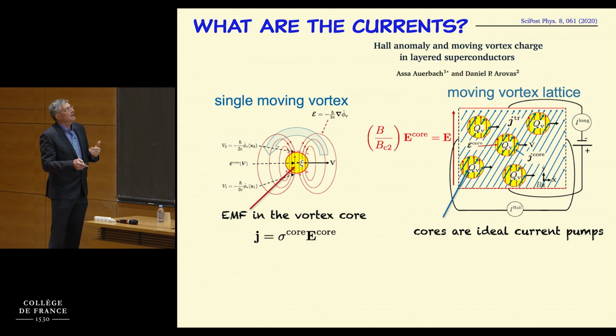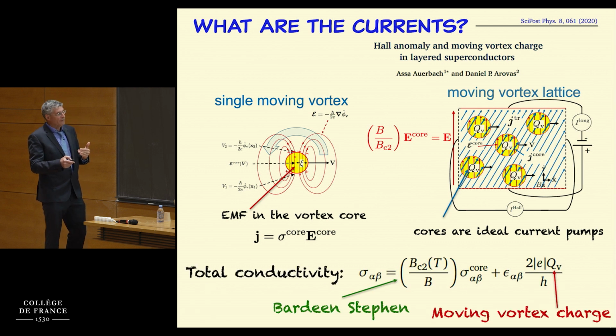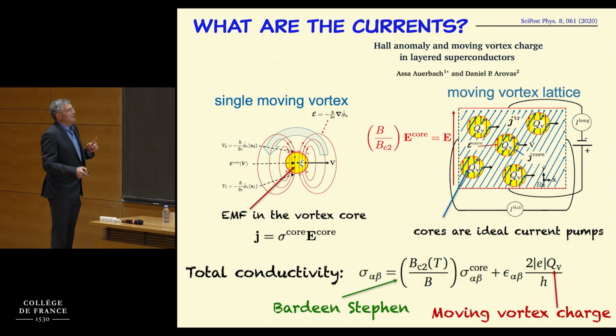And this will give us essentially this expression for the conductivity, not resistivity. So notice that we have a term that is exactly the term that we get from Bardeen-Stephen theory. So we recover Bardeen-Stephen theory for the term that comes from these cores. So these cores are now ideal current pumps, okay? And we know what the EMF inside them is, and using this expression we know what the current is. The current is flowing in a laminar way in the superconductor, so you have no vorticities, and therefore you know exactly the total current density that is produced by these current pumps. And that's the Bardeen-Stephen expression. So it's very simple.